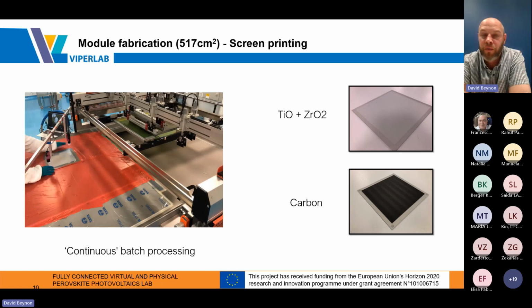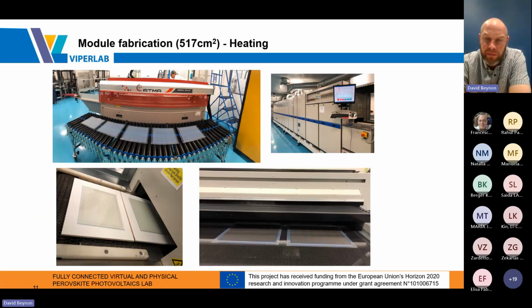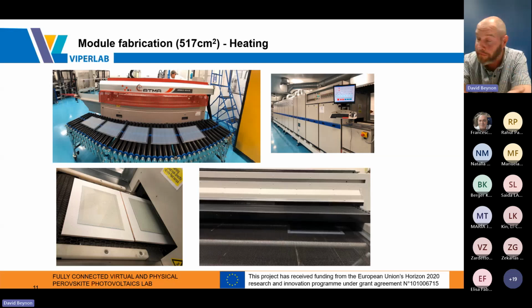So this is a screen printer that can do 1 meter by 1 meter print area. In this case, we're doing a 30 by 30 centimeter module. We screen print the titanium zirconia, and then come back to do the carbon on this printer. We then will anneal them. So we first do a solvent removal in our web heating process, and then we have an inline conveyor fed Henley furnace. So we'll actually batch process these. So we'll send the modules into the furnace, heat them up to 500 degrees, and then importantly cool them down again before taking them out.